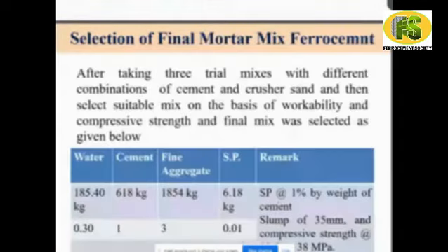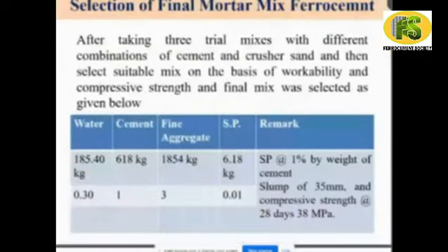This is the selection of the final mortar mix. Here we have considered the water to binder ratio, or water to cement ratio, as 0.30. Cement, sorry, this is the super plasticizer, 0.01%, and we are getting a slump of 35 mm, and the compressive strength at 28 days is 38 MPa. After making the mortar of this proportion, that means 1:3 is the proportion, water to cement ratio is 0.30 with super plasticizer 0.01%, and the compressive strength after 28 days is 38.